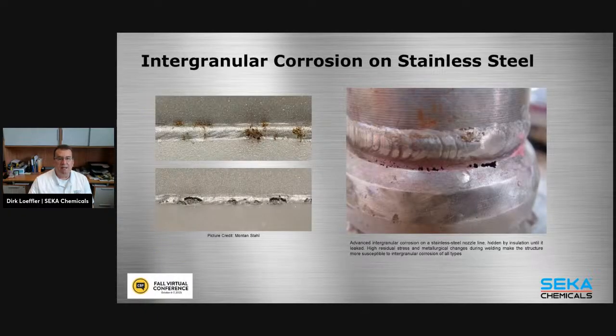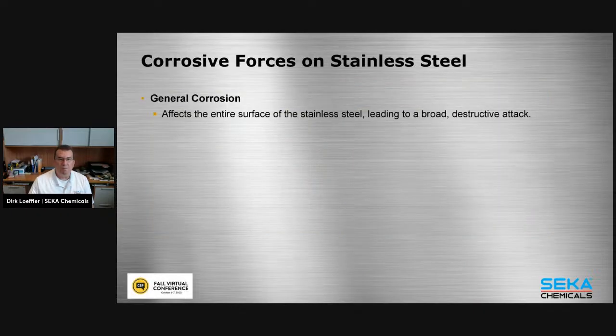This is what this kind of looks like. Typical different stages. This is probably how it starts. You see those along the welds generally. You see those rust marks. Then eventually, if it continues, you see that the weld will actually fail. Same thing here. This was under insulation and wasn't really caught until it finally started leaking. So a typical example of intergranular corrosion.